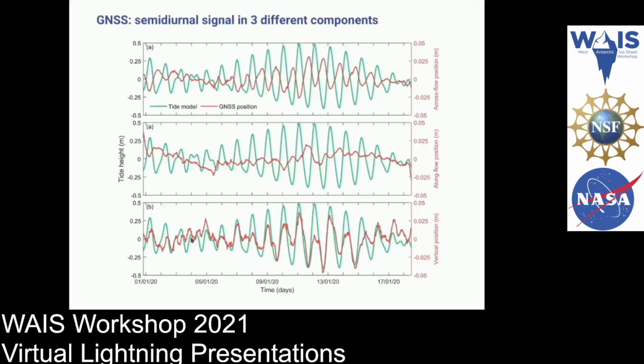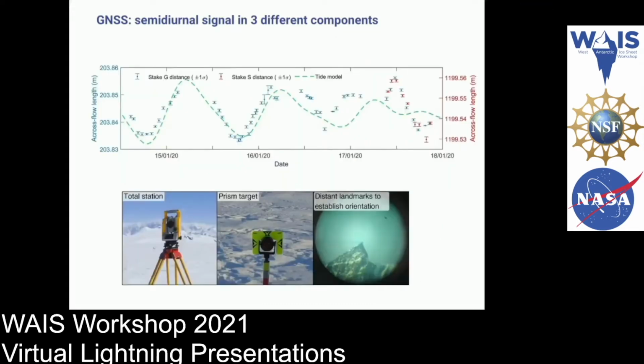And here in the backdrop you have a modeled tidal forcing. The second data set is these very impressive total station measurements that were carried out over 4 or 5 days that give a very accurate measurement of the strain on the surface of the glacier out to 200 meters and 1,200 meters in red from camp.